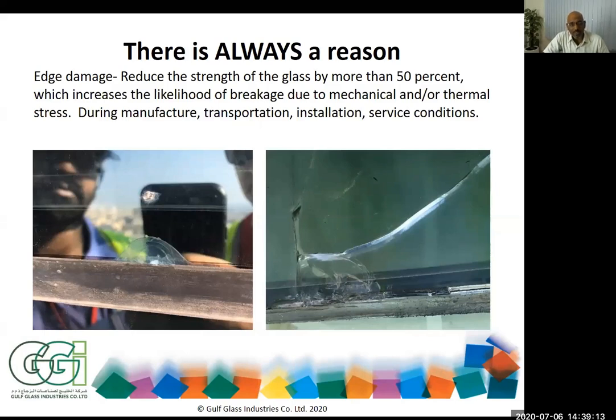And so when we went there, there were glasses which were broken. And when we did an investigation, we only saw edge damages. And through these edge damages, the glasses were propagating the cracks and leading to glass breakages. And it was happening only on one side of the elevation, because that elevation was getting most of the temperature, most of the sunlight, and also the wind.